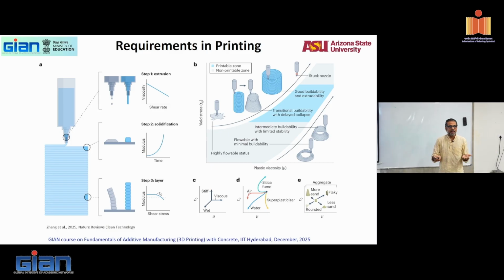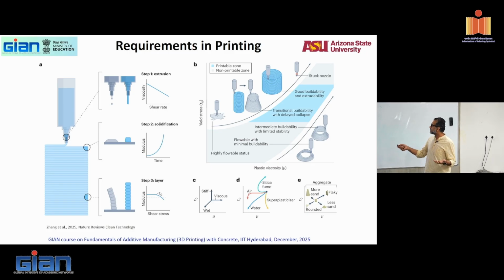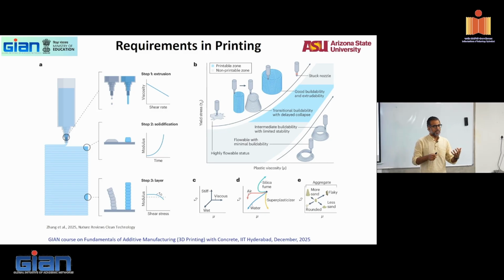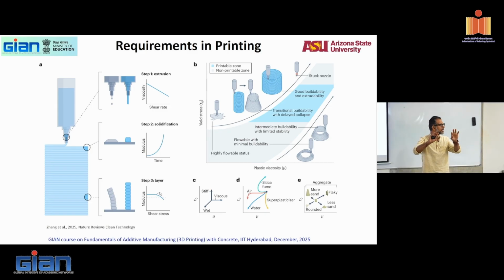Right? Which means that's where it is. Okay. Can I build that up then? It'll flow faster. Can I keep building up layers? Probably not. Minimal buildability at that state. Now, if I increase the yield stress a little bit more, I can start to make it much more buildable. I now want to introduce to you one more concept which we have not really covered, but I'm sure you are able to extrapolate from what we have learned. If yield stress is that stress which is required to initiate flow, because you have that yield stress and then beyond that the flow starts, we also talked about the idea that that is what is required to break that network. Break the network of particles so that it will start to flow. So, breaking the network meaning what?